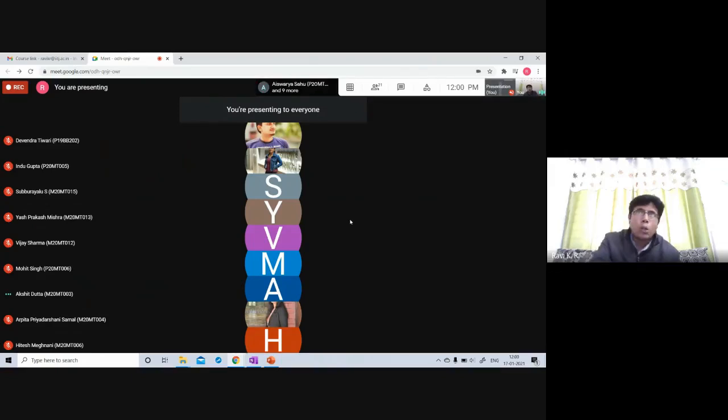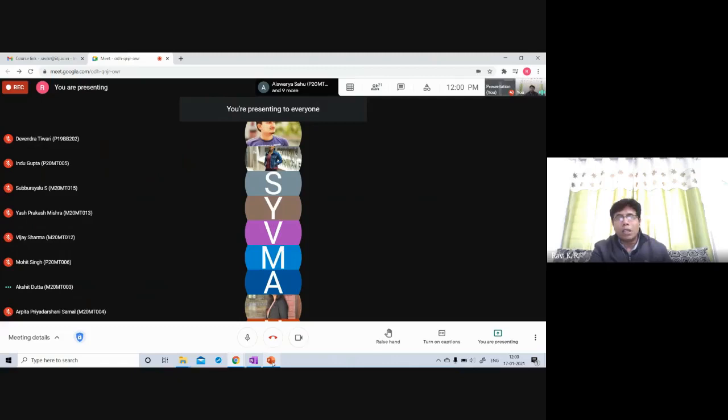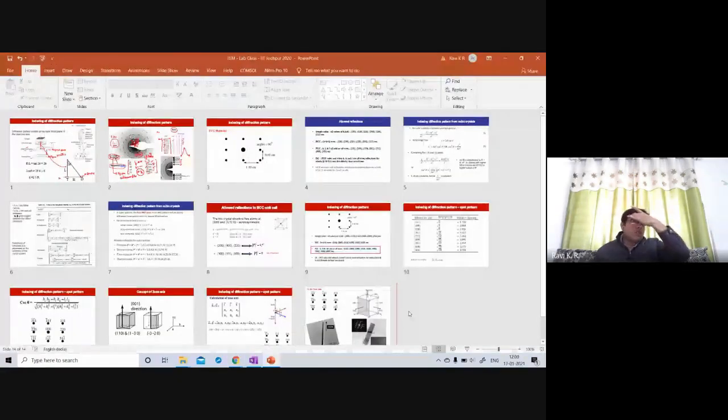It is as good as what you do in the normal X-ray diffraction method, where you have a standard 2 theta value and you compare the 2 theta in a PDF file. What you do here is you have a standard pattern. The only thing is you measure that distance, you inverse it, then you compare with your standard patterns. That's all. That is the difference here.